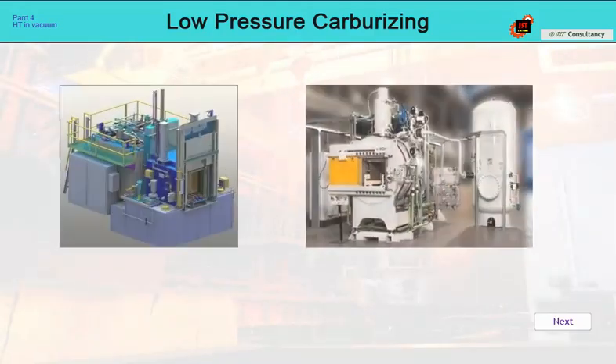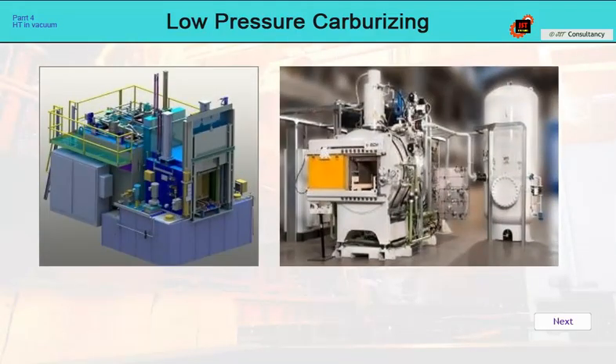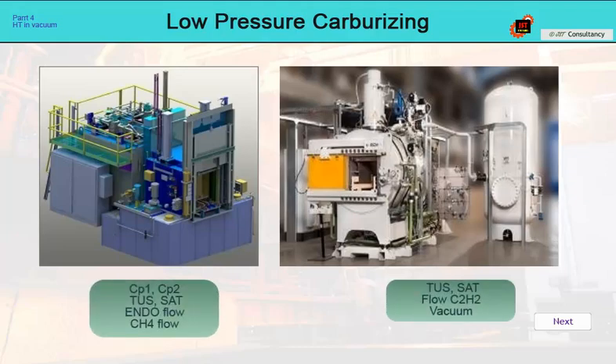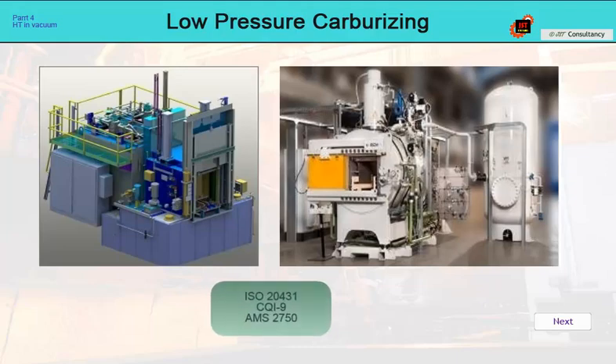Finally, I would like to mention the cost of equipment validation. Every device must undergo regular inspections to make sure that the achieved vacuum, working pressures, or flow rates correspond to reality, and the same applies to temperatures. We must be sure that if we set the required temperature of 960 degrees Celsius on the furnace, the actual temperature will be exactly that. How this is done is described in ISO 20431, CQI 9, or AMS 2750.